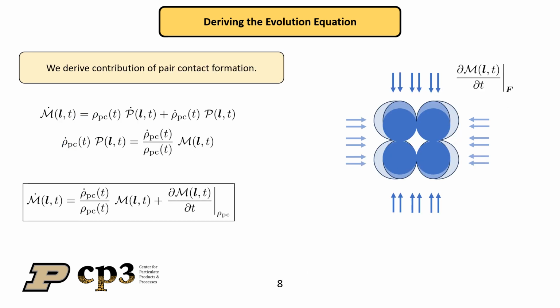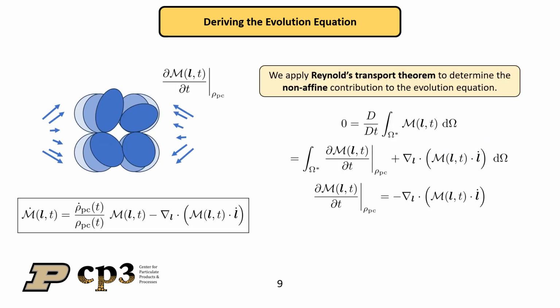We now show the derivation of the pair contact contribution, and we see that it is a simple scaling of the evolution of pair contacts by a normalized version of the microstructure. We now derive the non-affine contribution to the evolution equation, and by assuming a fixed set of pair contacts, we're able to use the Reynolds transport theorem to then obtain that contribution in terms of the rate of L.